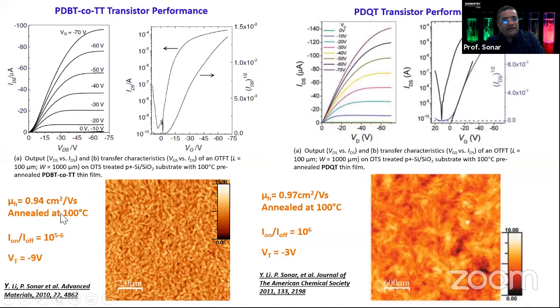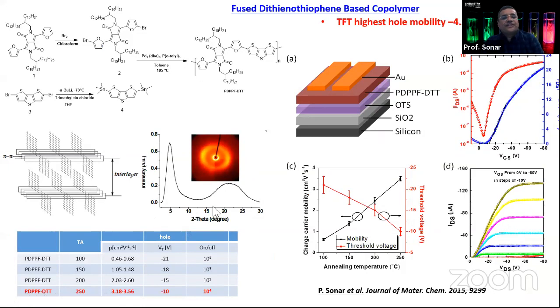And then, just by minimum annealing... again, the industry people were telling us, can you reduce this annealing temperature instead of going crazy, 250? We don't have a plastic film that can tolerate that high temperature. We just wanted some material that can be annealed under very mild conditions and still give a high mobility. And these two polymers, annealed at just 100 degrees Celsius, can achieve a very good hole mobility of 1 centimeter square per volt second.